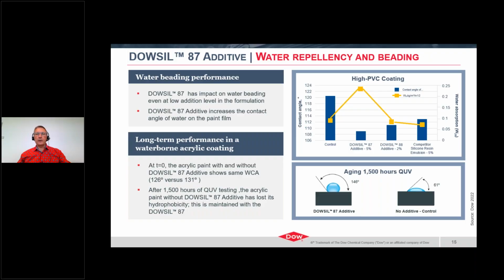Coming back to the exterior durability, the good exterior aging properties of the resin-based additive and of silicone material in general can be seen by the observation of the water contact angle of coating with or without the additive after 1500 hours of UV exposure in a QUV chamber. While both of the formulations started with very comparable contact angle, after 1500 hours of UV aging, we can see that a significant difference can be observed, with a reduction of more than 60 degrees of the water contact angle for the formulation free from the silicone additive.